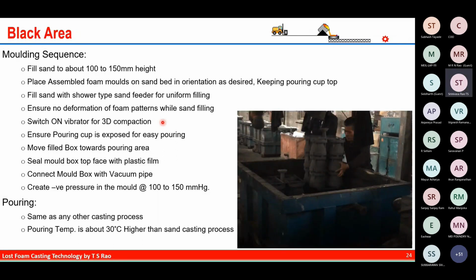Ensure pouring cup is exposed for the easy pouring. Always we have to ensure that the pouring cup is exposed for pouring. And move filled boxes towards the pouring area. After this, the top surface of the mold should be covered with a stretch plastic film. Then the vacuum pipe is connected to the mold box to create the negative pressure in the mold to 100 to 150 mmHg. This is mainly to take out any fumes or gases or air in the mold between the sand particles, and also it will promote the mold filling. The mold filling is going to be much faster than sand casting because already there is a negative pressure created in the mold box. That is why even the casting is sound compared to sand casting process.